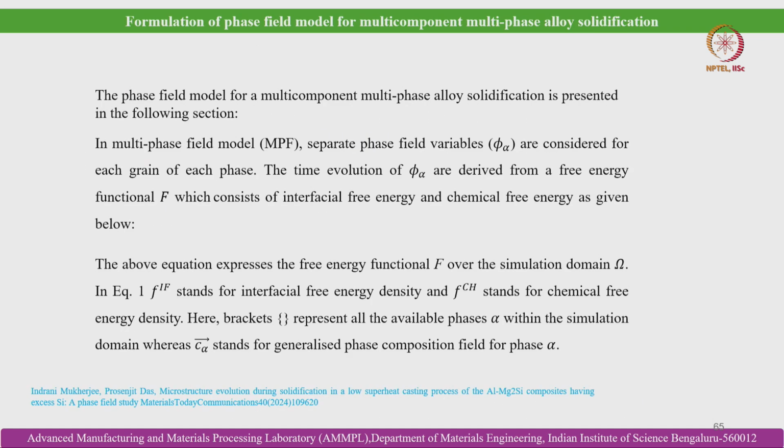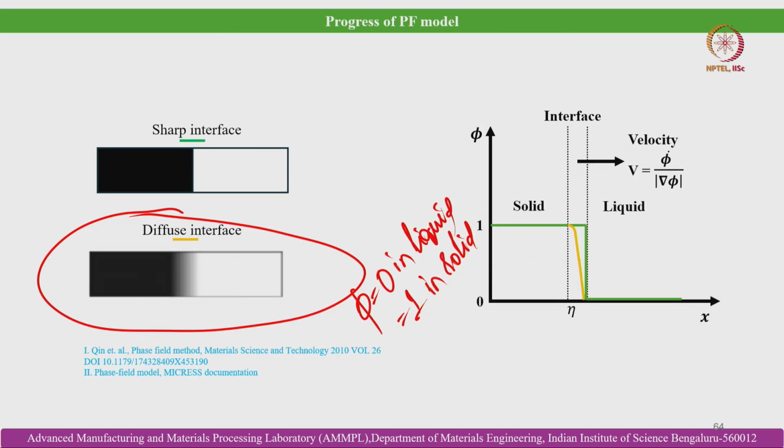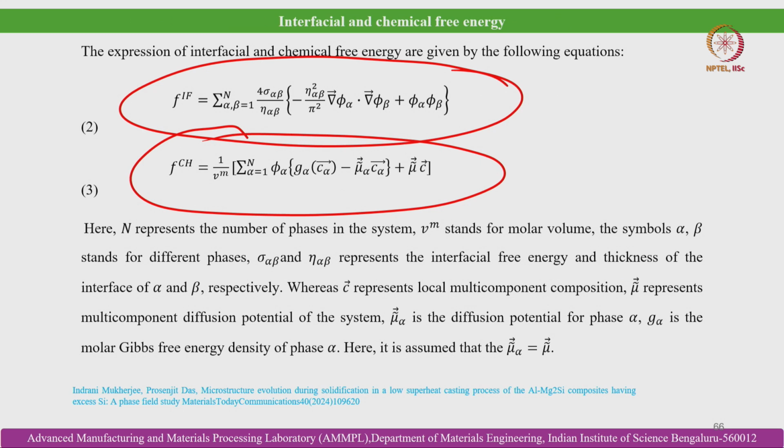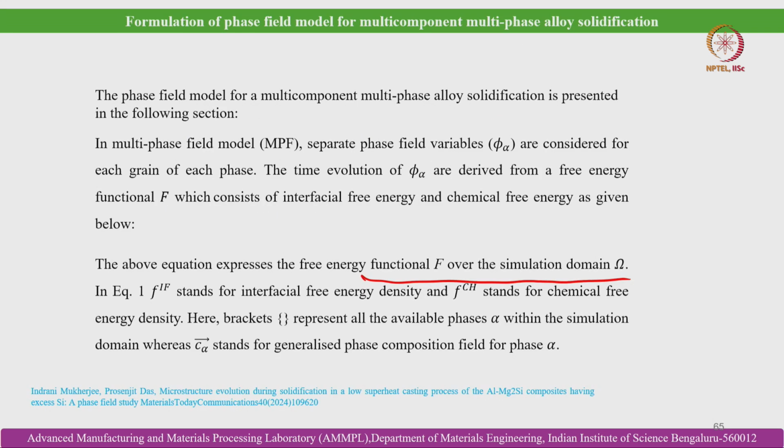Here this expression gives the free energy functional F over the simulation domain omega. So, in equation 1, F_IF stands for the interfacial free energy density and F_CH stands for the chemical free energy density.